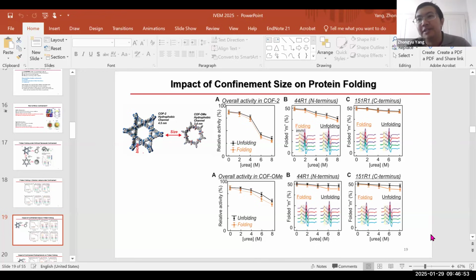Because it depends on how much is loaded and also on restriction, right? Substrate diffusion, etc. So for this activity test, it's the same enzyme, but this time we cannot use a bacterial cell wall as the substrate. We use a smaller substrate that can diffuse into the channels and the cages of the COF. So diffusion rate and loading capacity are very difficult to calibrate.